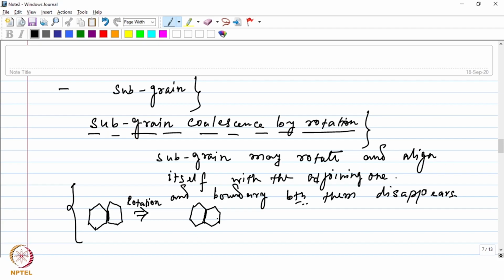And now when this merged subgrain attains the critical size, it can act as the nucleus of a strain-free grain. Okay. So what I meant to say when I say that there is some orientation difference, so that is in terms of the atomic arrangement that you have. So if this be the arrangement in the first subgrain, in the other one it is little different across this boundary. Okay. Therefore, these two different arrangement, for them to align into one, you need some rotation, right?